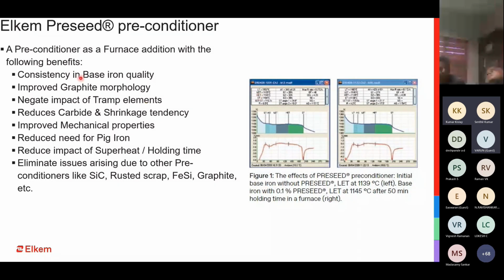It improves the quality of the base iron, makes it consistent, improves the morphology of graphite, negates the impact of tramp elements or trace elements, reduces the tendency for carbides and shrinkage, improves the mechanical properties, reduces the need for pig iron. We talked about pig iron bringing in unknowns into our system, and still we are dependent on it for a lot of nucleating benefits that it brings with it. But the need for pig iron can be reduced or may need to be reduced, and that is where preconditioning helps. It reduces the impact of superheating and holding time.